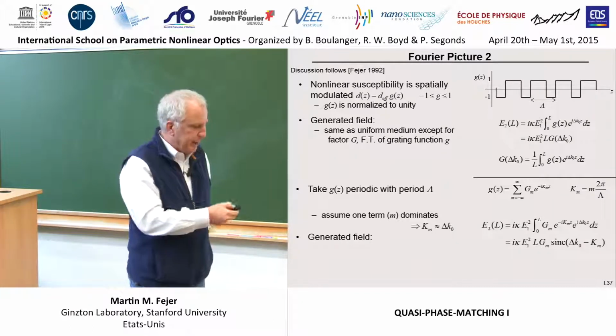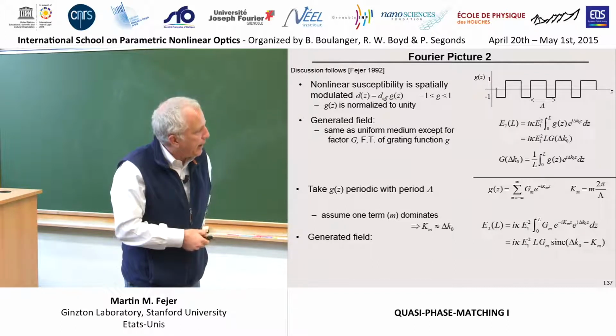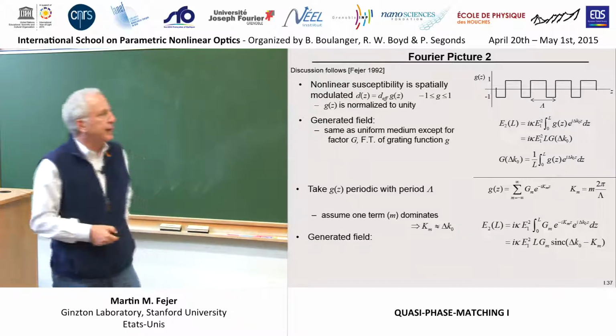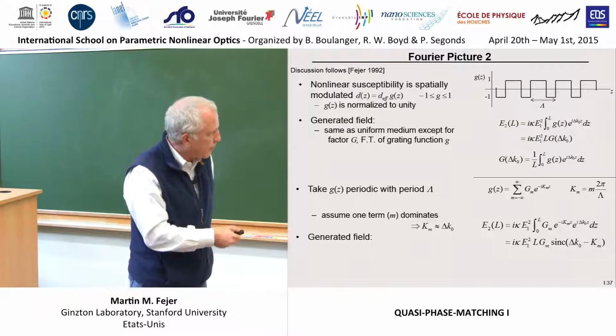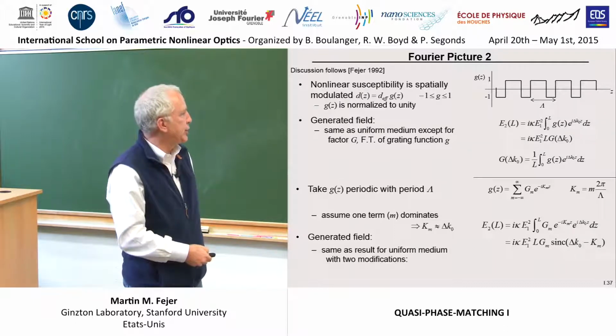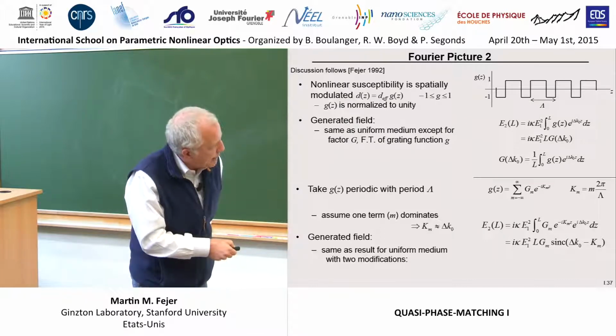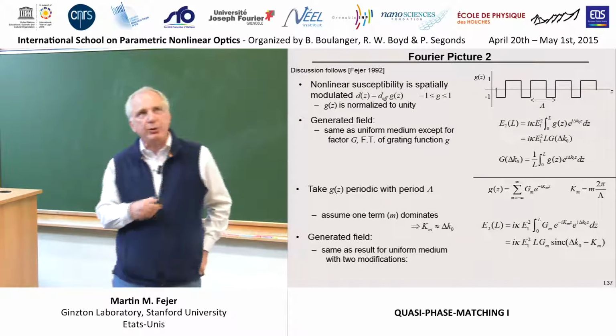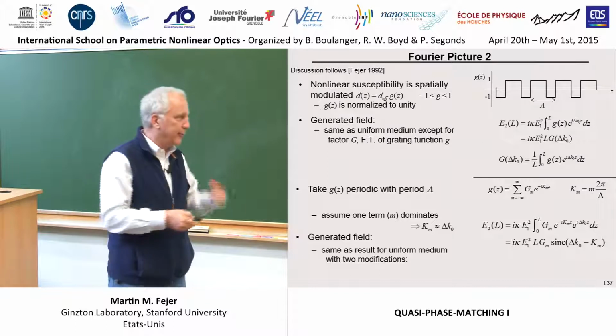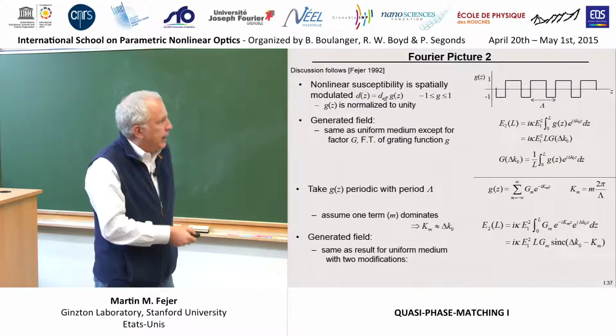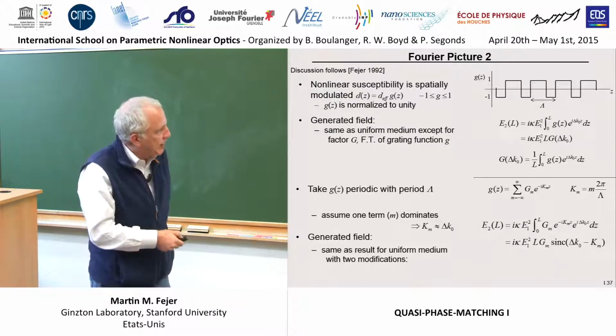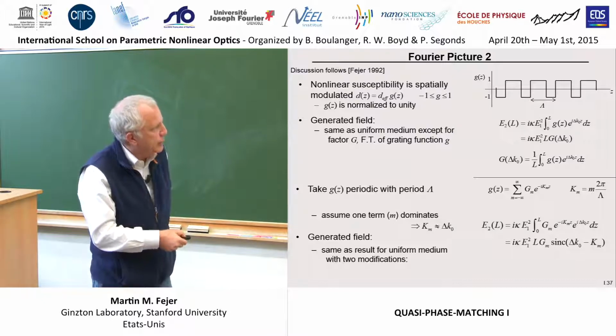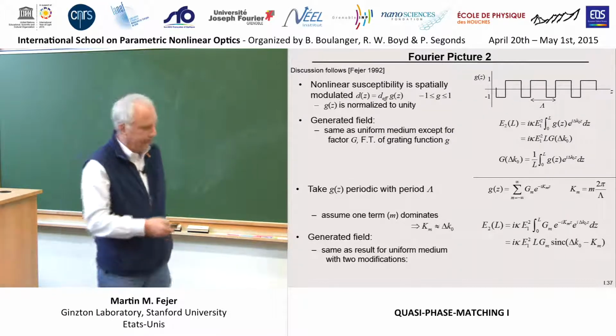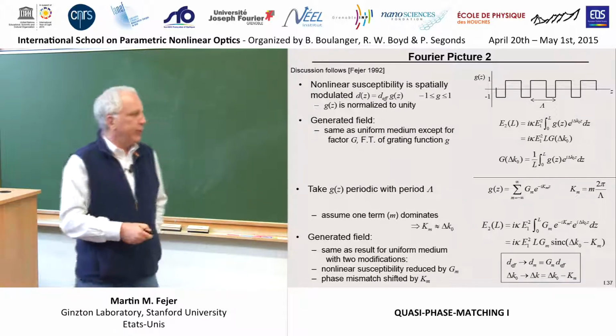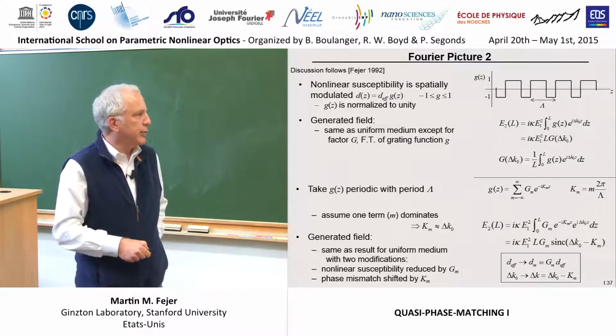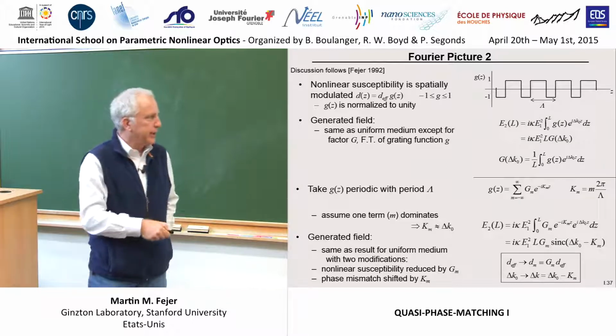So if we do that and we put our expansion into our integral here and keep only the term that's close to phase matching, what you find is that the second harmonic field looks just like it would have had this been a phase-matched medium with two changes. One is, as we said, you don't want phase matching anymore. You want delta k equal to one of these grating k vectors, Fourier components, k sub m. And the other is, instead of having a nonlinear coefficient d effective, the thing out front is reduced by whatever the amplitude g sub m of this Fourier component of our grating is. And we'll take a look at that in a second. So with these two transformations, you take d effective to g sub m times d effective, and you take delta k to delta k minus k grating.